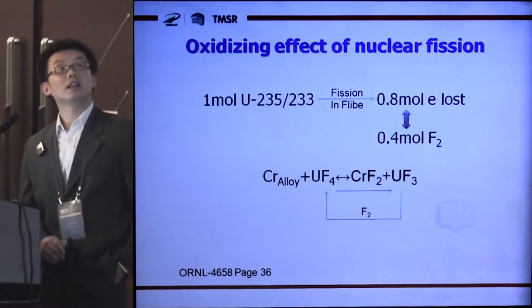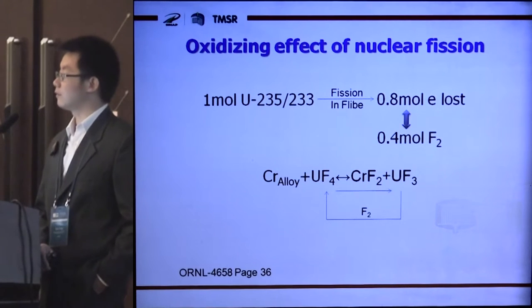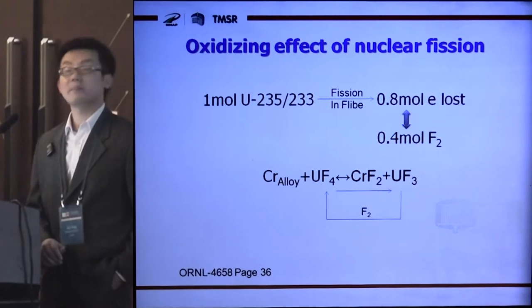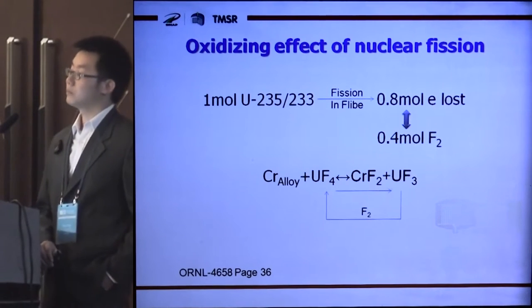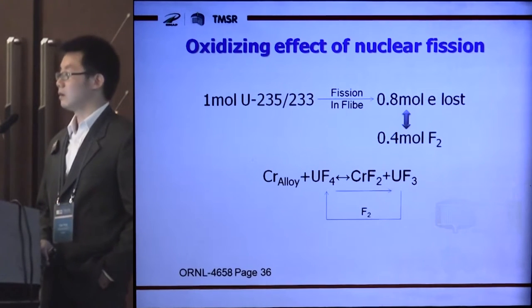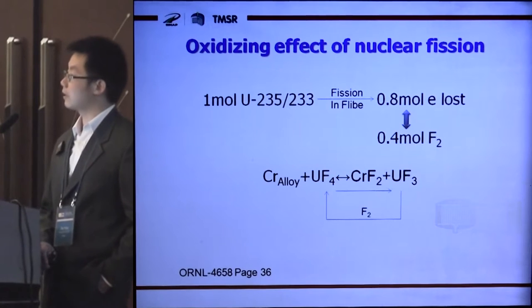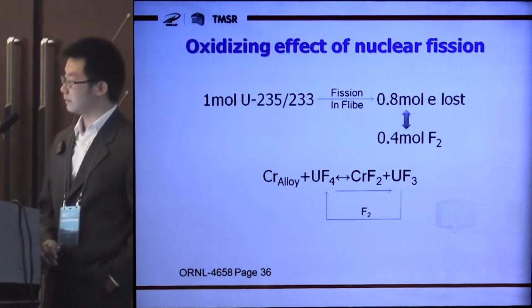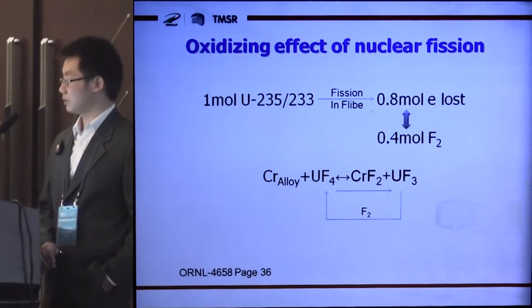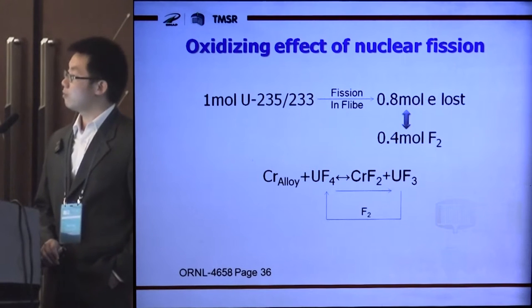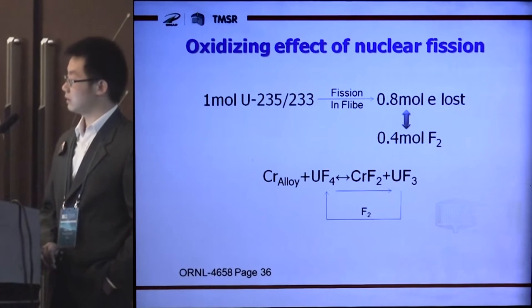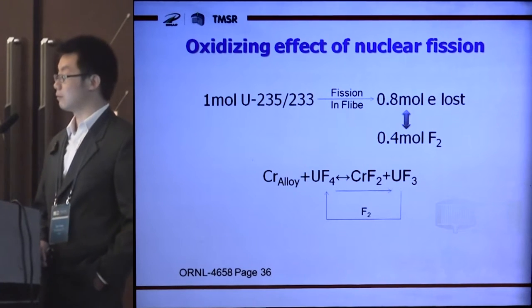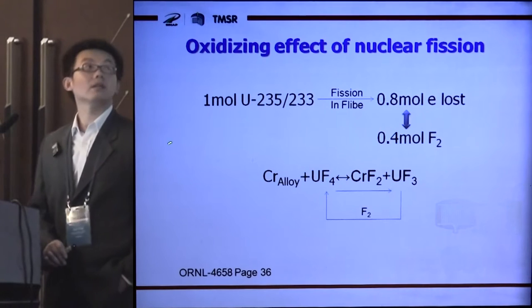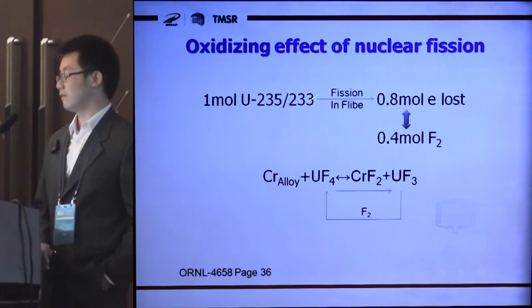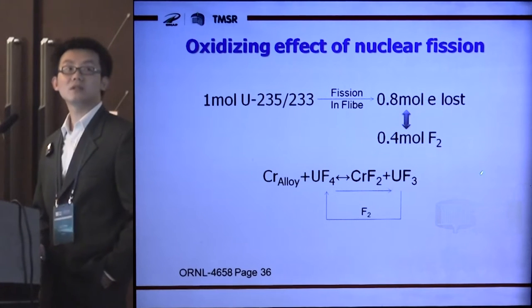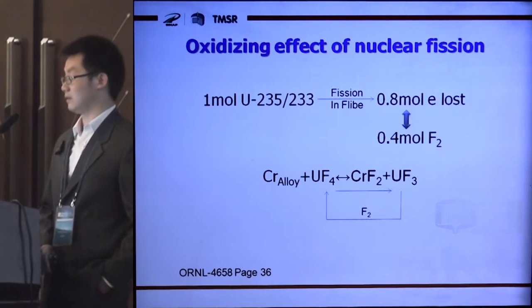This slide shows the oxidizing effect of the nuclear fission. From the experience of MSRE, when one mole of uranium undergoes fission in the reactor, about 0.8 mole of electrons will be lost and then cause an oxidizing effect. In other words, about 0.4 mole of fluorine gas can be produced when one mole of uranium is consumed in a reactor. Actually, this is a slight oxidizing effect, but it may cause the corrosion reaction to go in a worse direction.